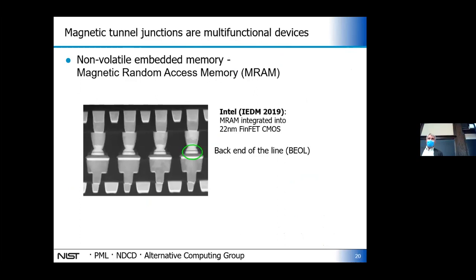Here is an SEM image of a magnetic tunnel junction integrated into the back end of the line — you take a semiconductor surface, make all the transistors, grow the metal wires on top, and then grow magnetic tunnel junctions there connected to the transistors. This is a technology that exists at high-end fabs in cutting-edge technologies. These are being developed for non-volatile memory in different types of applications, but if we can do something close to that, we're pretty close to the technology.